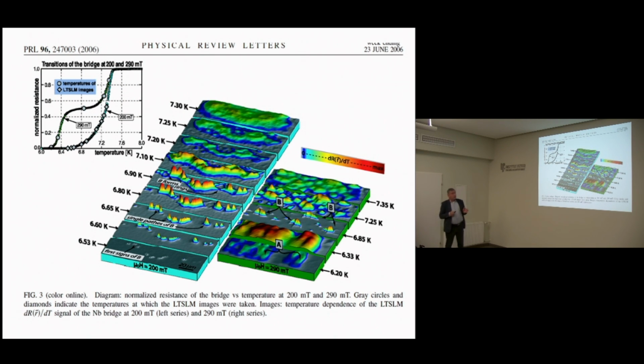And in this experiment they made a bridge. The bridge had around 40 micron width and 130 micron length. And they used the so-called scanning laser microscope. It means what they did is they illuminated the bridge with the laser. It means they heated the bridge. And nevertheless, the areas underneath have different Tc. And they measure resistance in situ using lock-in technique. And here you see the results of such measurements.